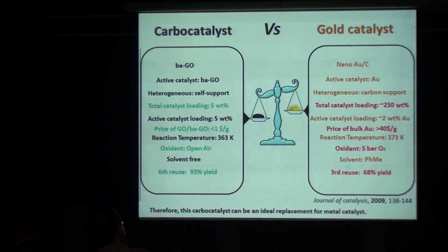They have to support the gold on carbon. They don't just disperse gold in a solution. You cannot recover it. So the gold has to be supported on carbon. And the amount of carbon that they use is a lot for the conventional catalysis. The total catalyst loading is 250 weight%.